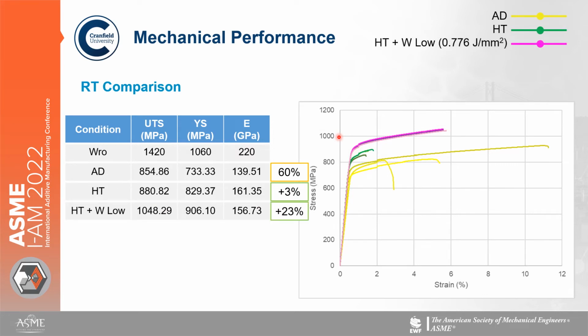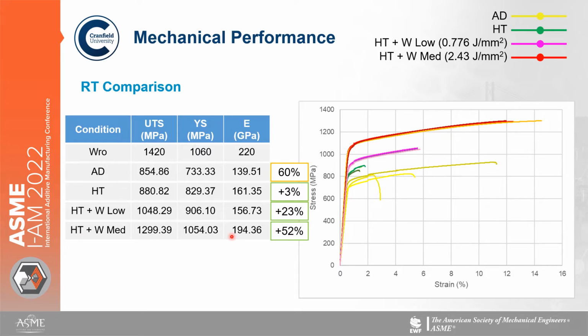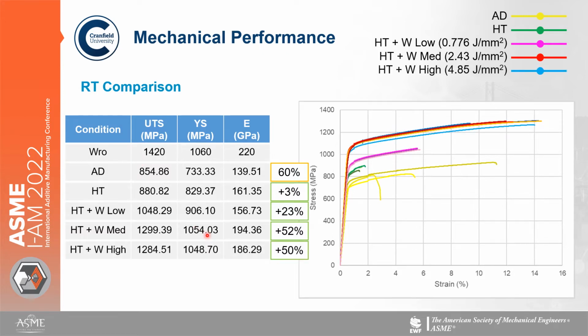And then when this heat treated material is worked at our lowest input energy, which is our highest peening tool travel speed, we get a 23% increase in our UTS versus the as deposited material. And then again, when this material is worked at our medium input energy, we get a 52% increase versus as deposited material. And then at our highest input energy, which is our slowest peening travel speed, we get a 50% increase versus as deposited material. And you can see that once it gets to the medium input energy, there isn't a great deal to be achieved more by inputting at a higher energy.